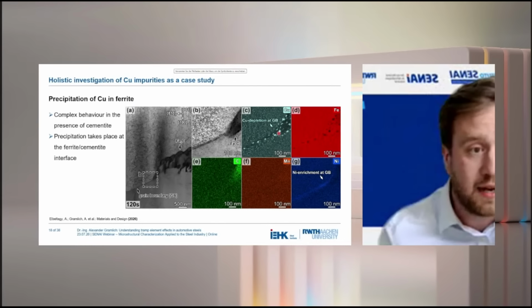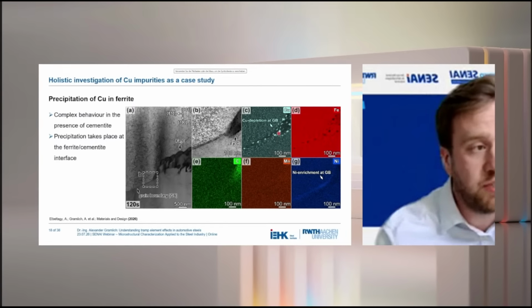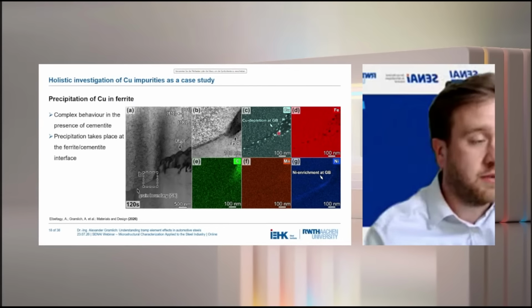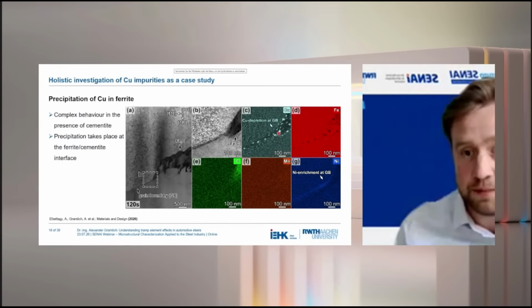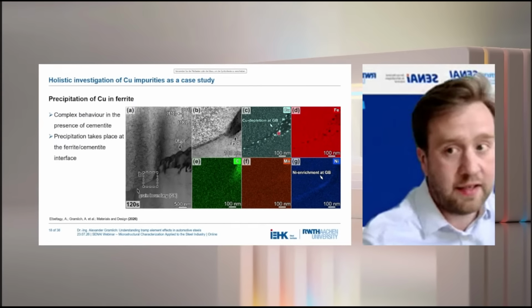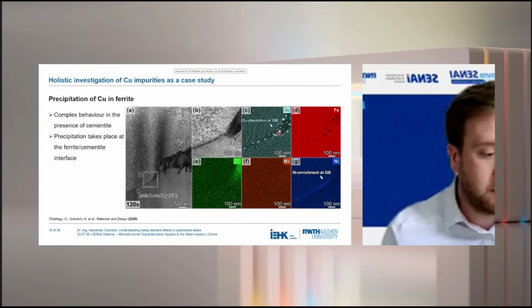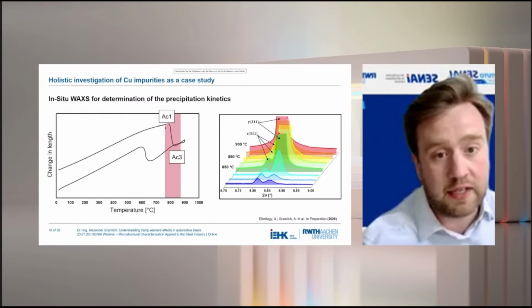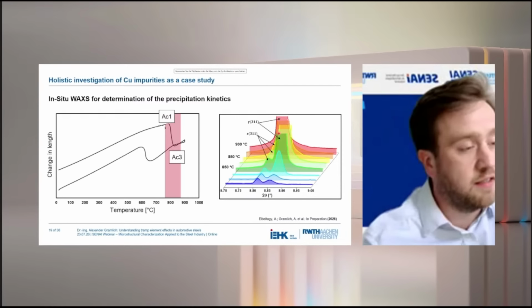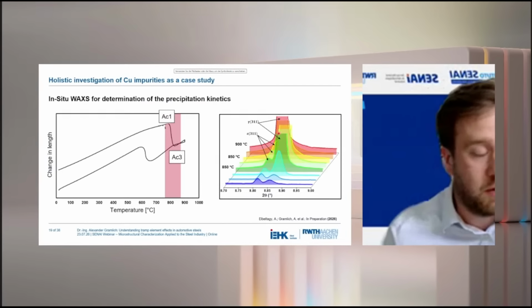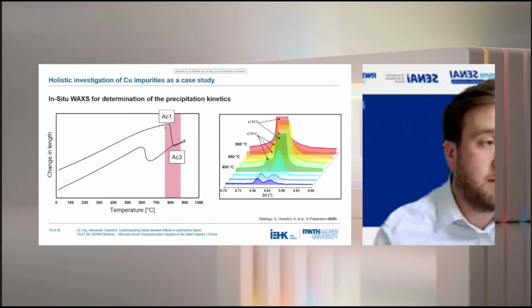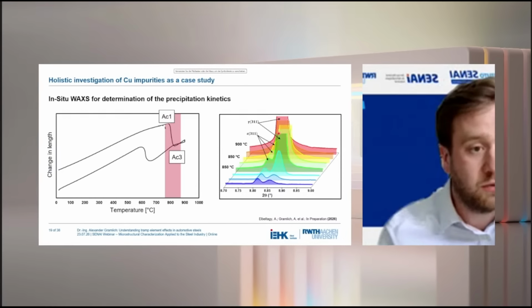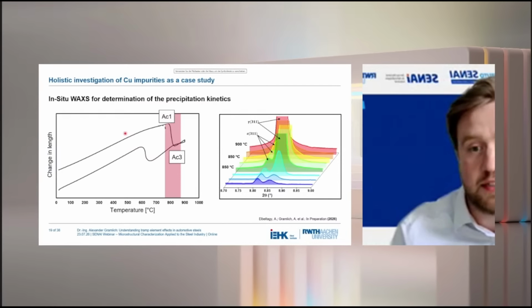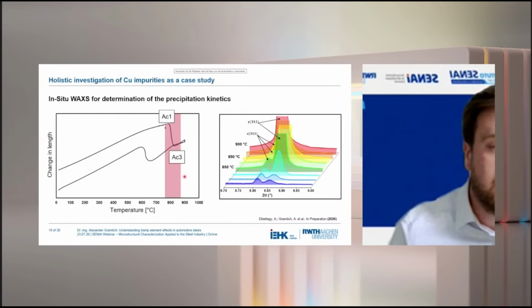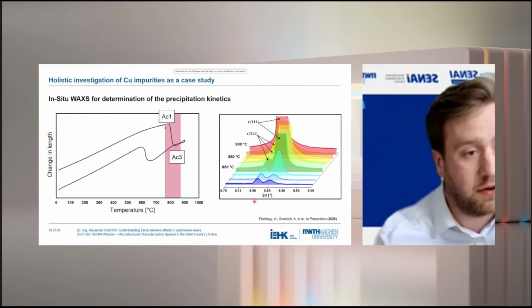So you could argue now, okay, how do these alloys or how do these precipitates really form? Basically, you can only learn this from in situ observation. And this is what we are working on at the moment. For this, we went to a synchrotron source for X-rays, and we did dilatometric investigations of our copper-alloyed steels and measured the crystallography in situ. And you can see here on this side our heat treatment and the change in length. And on the right side, you can see our X-ray results, which we collected during the quenching.